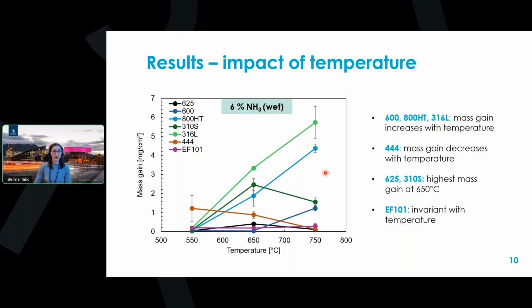The next graph here shows the impact of temperature, which was studied at 6% ammonia and wet conditions. In this case, we see that alloy 600, 800 HT, and 316L all have an increasing mass gain with increasing temperature, meaning they become more nitrided. While the ferritic stainless steel 444 actually shows the opposite trend. Here we see that as we go from 550 to 750, the mass gain decreases. The alloy 625 and 310S had the peak at 650 degrees centigrade, but again, 625 was quite low on mass gain at all conditions. And finally, the alumina forming EF101 was quite invariant with temperature.